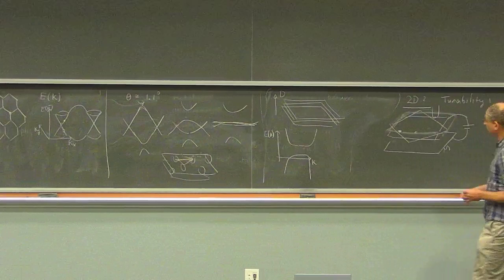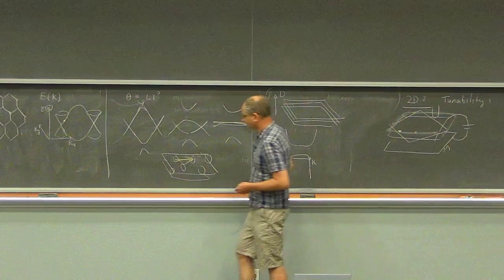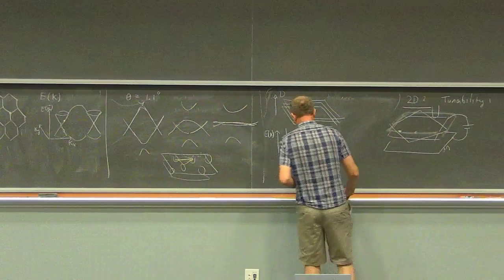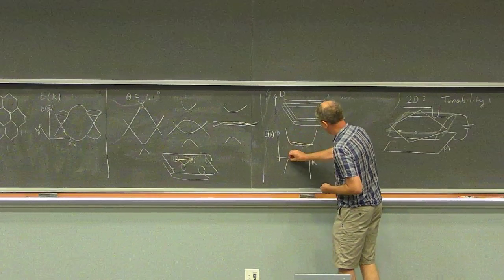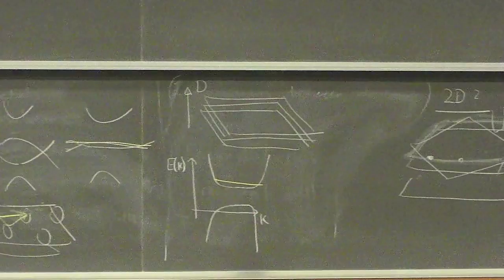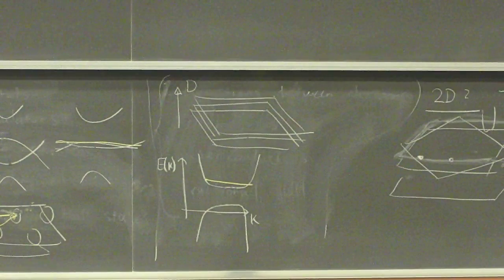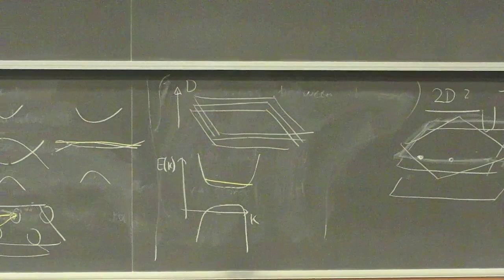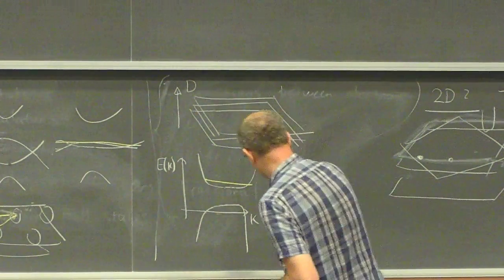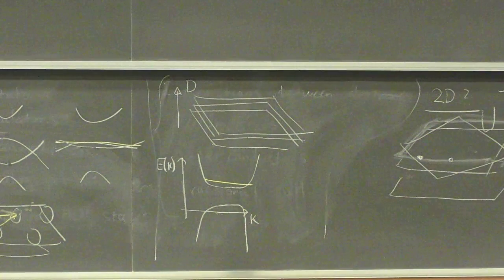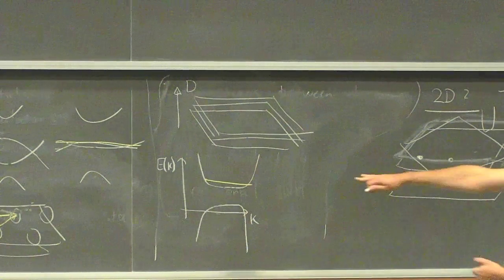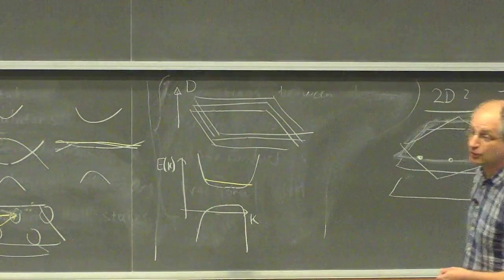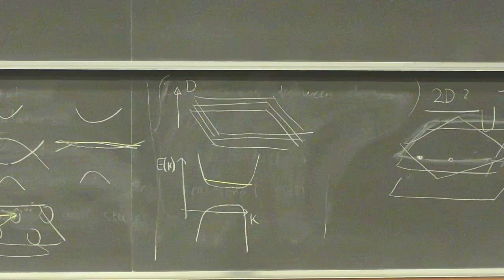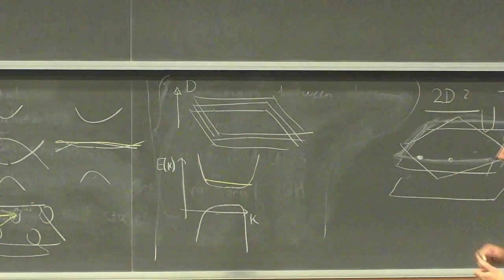And then you tune your density of electrons by a gate, somewhere to here or to there. And the electrons interact and form totally new states, including superconductivity. So the same class of phenomena can actually appear, we realize, even without the twist. And these systems are much cleaner, much more uniform, and simplify our life. I'm a theorist, my life in particular, they simplify a lot.